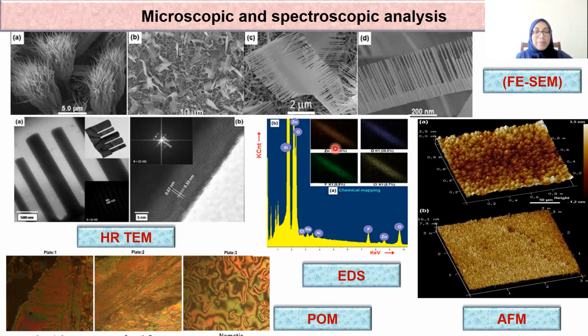nanomaterial. The elemental distribution of zinc oxide nanocomb on silicon substrate is analyzed through the EDS pattern, as you can see here. The development of zinc oxide nanomaterial is indicated by the high peak of zinc and oxygen. It also confirms that the zinc and oxygen occur with an atomic ratio of 24.63 to 18.34. Then additional elements like aluminum, fluorine, chlorine are also seen here.